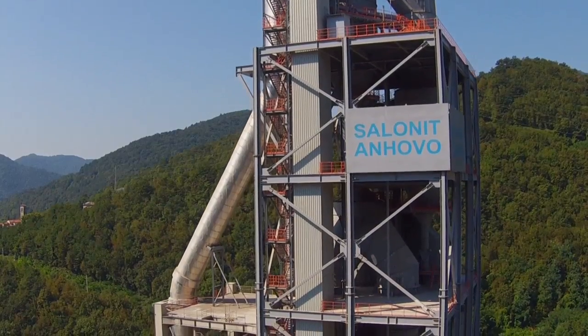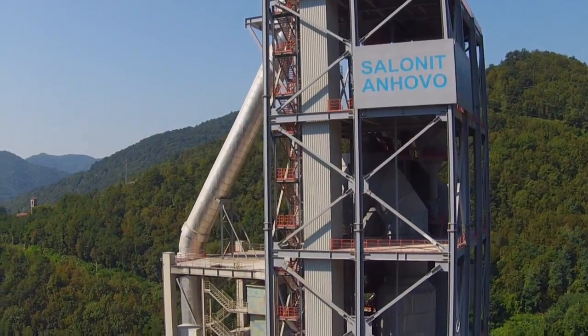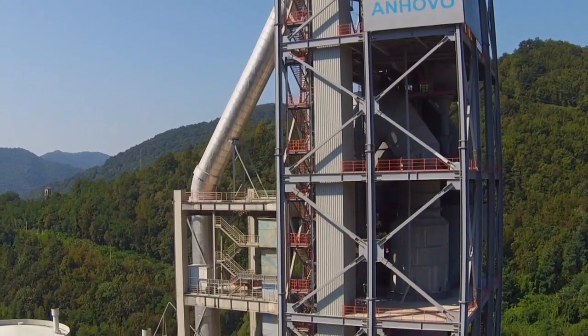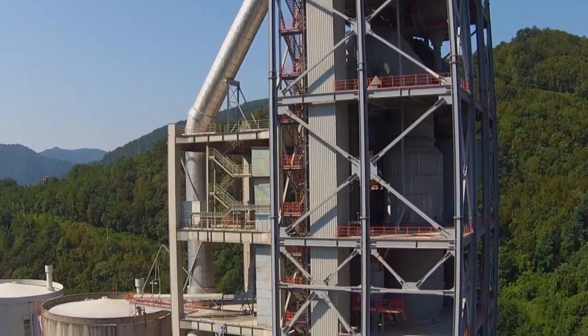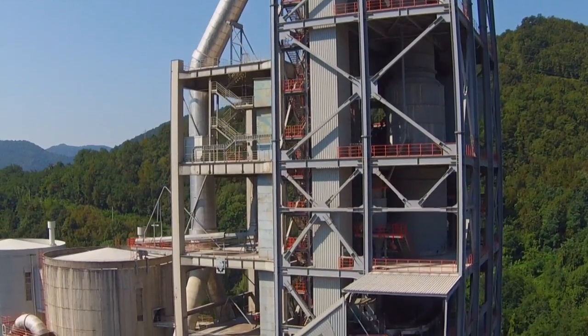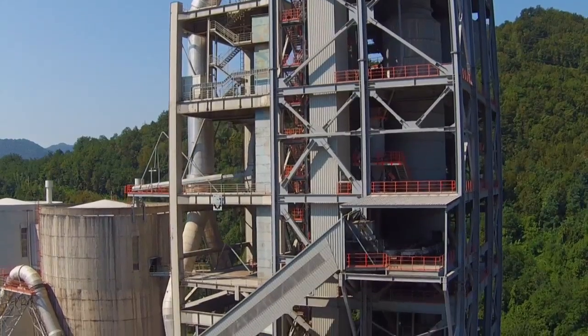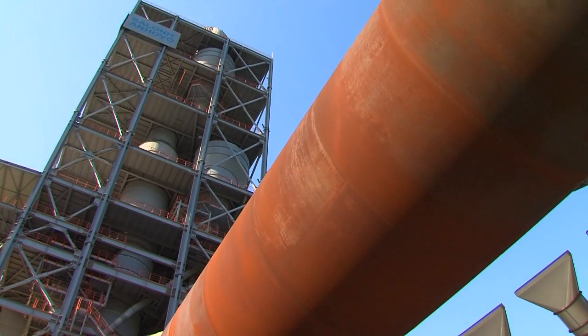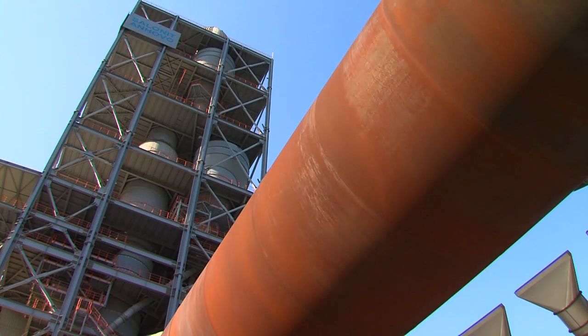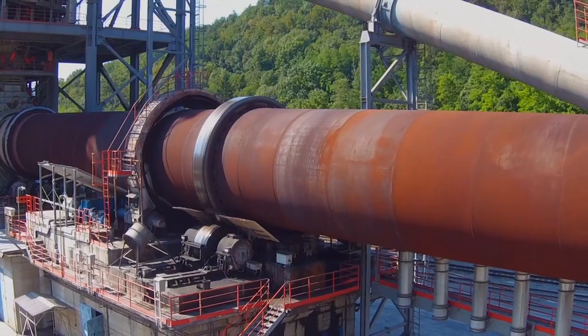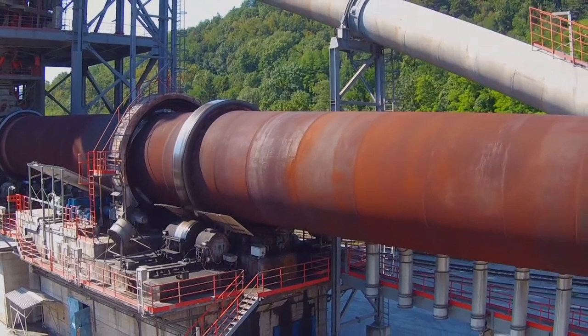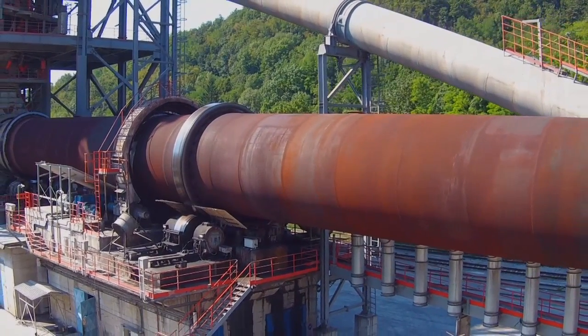Then it goes through a series of 5 cyclones and calciner, where drying, preheating, and decarbonization, thermal decomposition of carbonate minerals are taking place. Hot meal with a temperature of about 900 degrees Celsius enters the kiln in the cooler part. From there it travels toward the warmer part, where it reaches a maximum temperature of 1450 degrees Celsius.